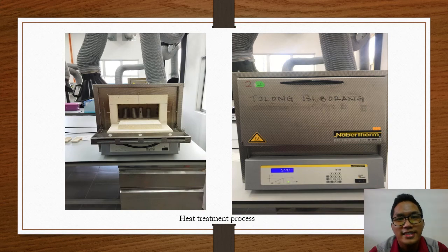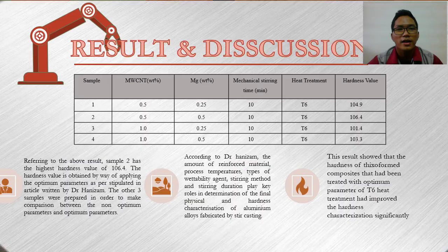After that, the part was heat treated with solution heat treatment at 540 degrees Celsius for 8 hours by using a Nabertherm furnace as shown. Hence, the solution heat treated part was quenched at room temperature of 27 degrees Celsius. After going through the process mentioned earlier, the result shows the sample to have the highest hardness value of 106 HV. The hardness value is obtained by way of applying the optimum parameter as stipulated in the article written by Dr. Hanizam. The other three samples were prepared in order to make comparison between the non-optimum parameter and optimum parameter. This proves that heat treatment with optimum parameter provides the best result of hardness value.